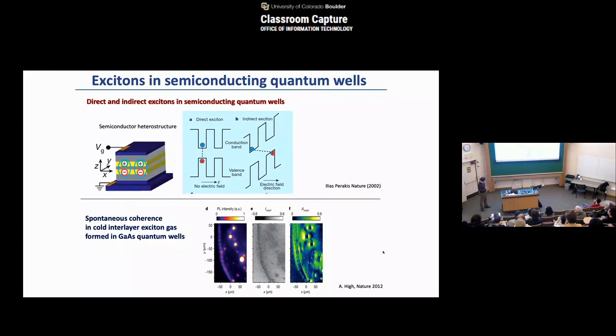Part of the reason is, although the exciton lifetime is long, it's not forever. It's still something like 100 nanoseconds. Part of the reason is basically that the cavity is confined, but not tightly confined. So there's a leak of the electron wave function or hole wave function, and there's some overlap that makes this finite lifetime.